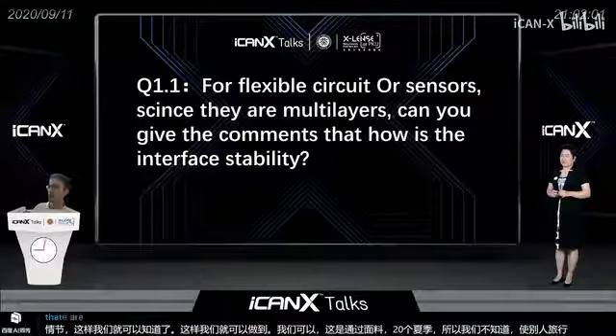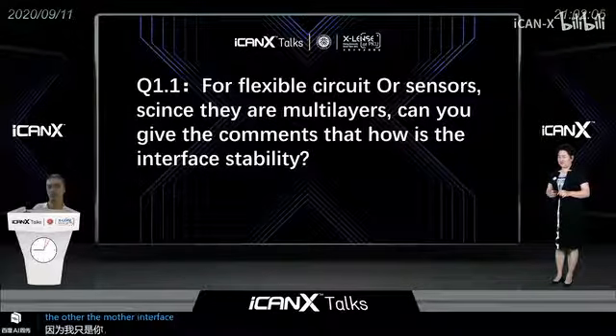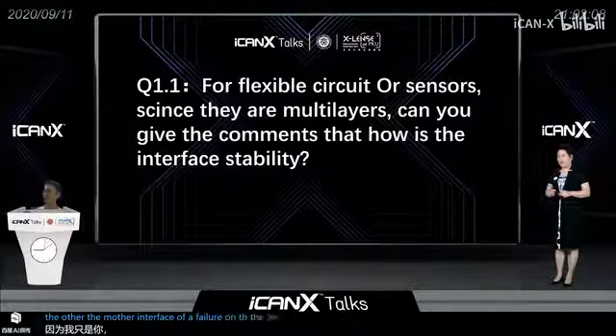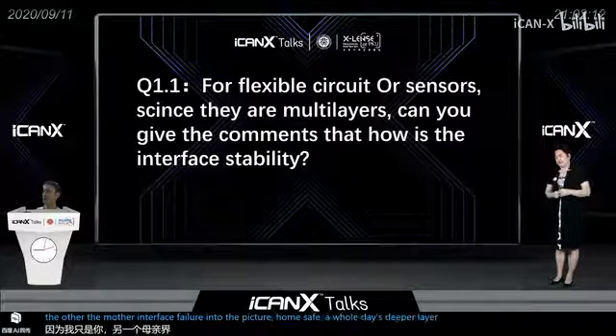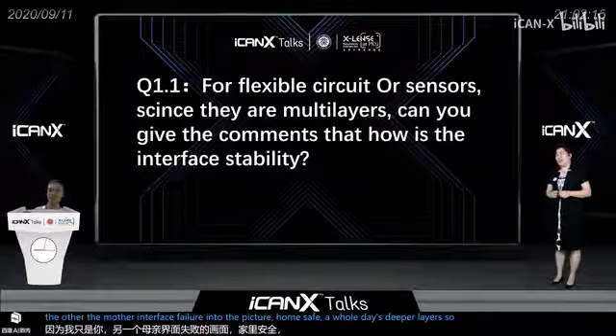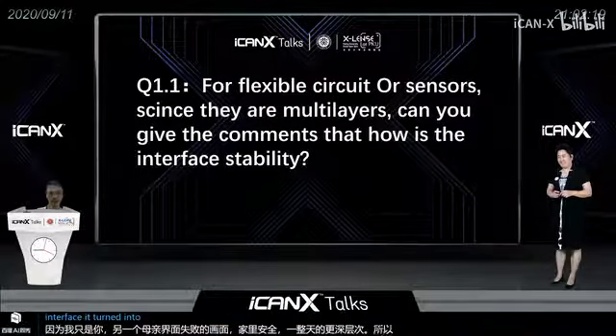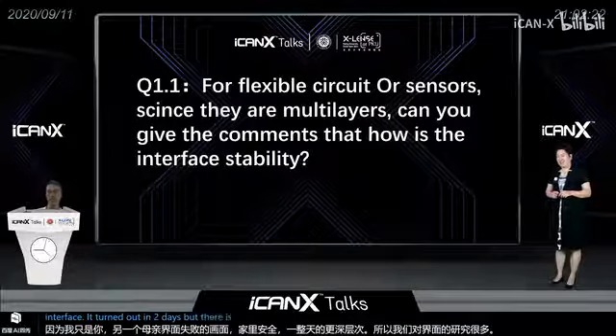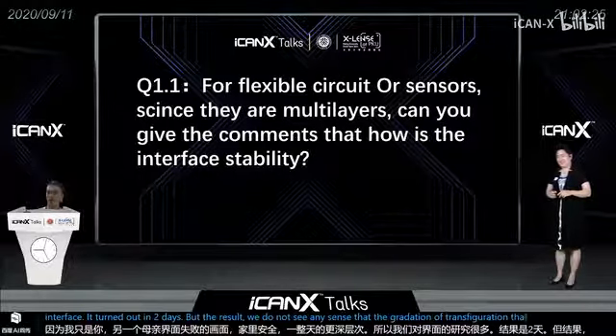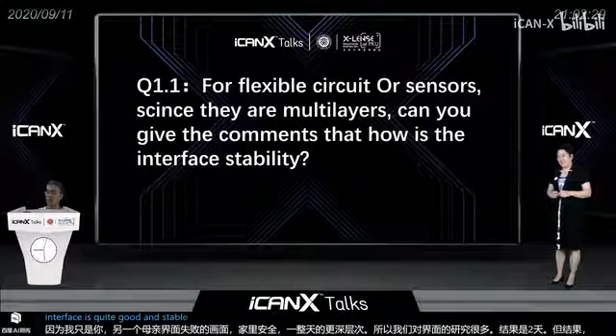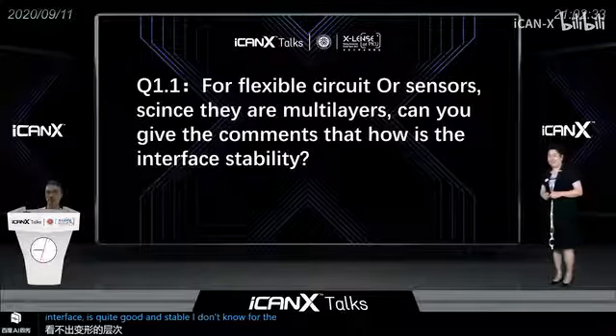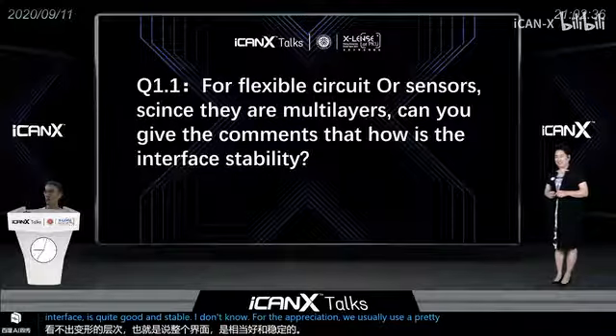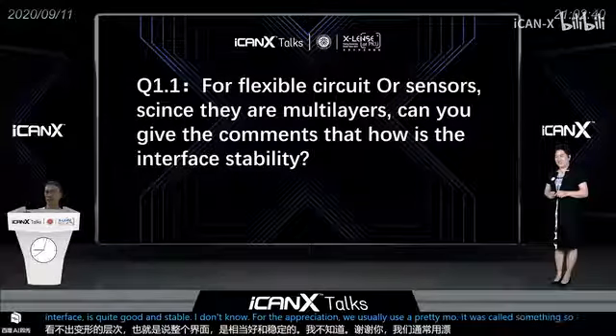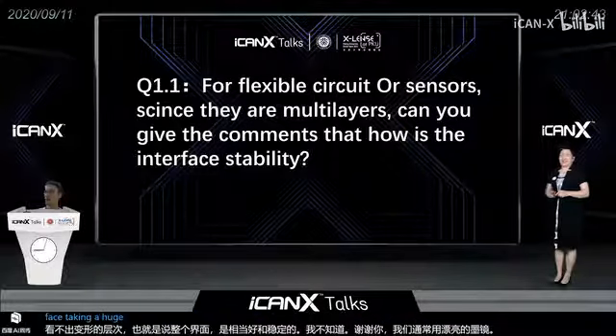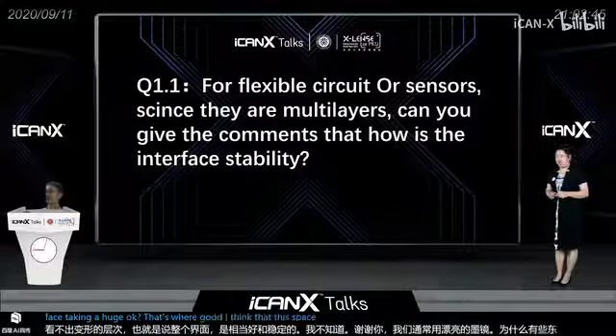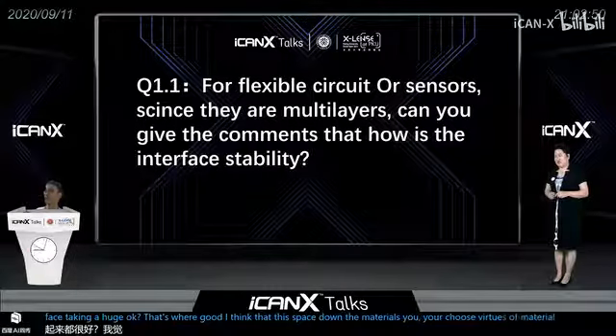Is that an answer? For the interface of the nanomaterial onto the flexible substrate, for these different layers. We didn't study so much about the interface between each layer, but based on the results, we don't see any sensor degradation or transistor degradation. That means probably the interface is quite good and stable. Also for the transistor application, we usually use polymer deposited by spin coater, so the interface has pretty good adhesion. Okay, that's very good. I think this is based on the materials you choose. If you choose more stable materials, it should be better.